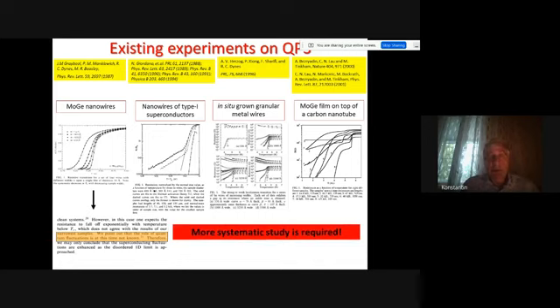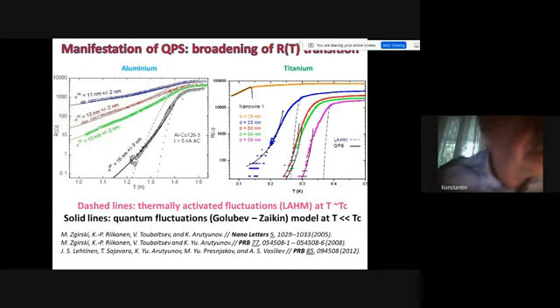So that was the beginning of our study, when we decided that we have to make something new and more precise. As I told you, we used our technique specially developed for this topic to progressively reduce the cross-section of a nanowire. Of course, we fabricated many structures, and all of them show a similar dependence. Let us, for concreteness, look at the left image. This is the resistance in logarithmic scale of an aluminum nanowire as a function of temperature. And just a reduction of a few nanometers in cross-section dramatically changes the shape of the resistance versus temperature dependence: 15 nanometers, 13, 12, 11.